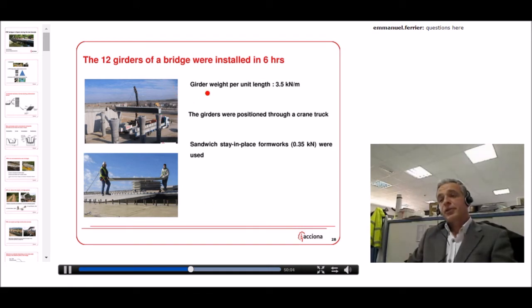Since we use glass and carbon and not full carbon girders, you have to pay a little bit in terms of weight. You see, we pass from 1 kilonewton per meter to 3.5 kilonewton per meter. But even in this case, you can see that it was possible to install the girder using a simple truck crane.